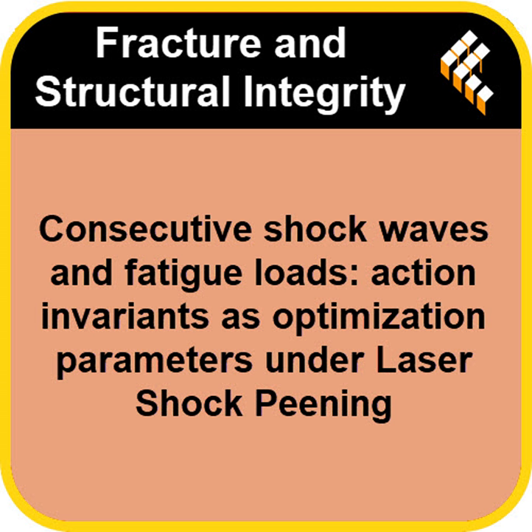And the result? Did it improve the fatigue life? It did. They reported an increase in operational characteristics, essentially fatigue life, by about 9 to 10% in the VHCF regime. 9 to 10% might not sound huge, but in aerospace, that's significant. It's very significant, especially in the VHCF regime where failures can be unexpected.